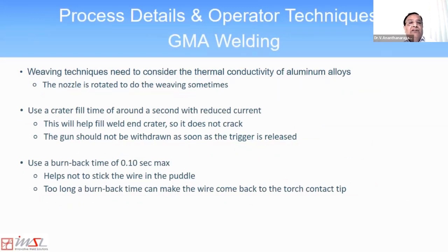And you can use a crater fill time of around a second with reduced current. This will help fill the weld crater so it doesn't crack. And the gun should not be withdrawn as soon as the trigger is released. And a burn back time of about 0.10 seconds max will help make sure that the wire tip ends in a sharp configuration and make sure that it doesn't stick to the contact tip upon the finishing of the burn back time.